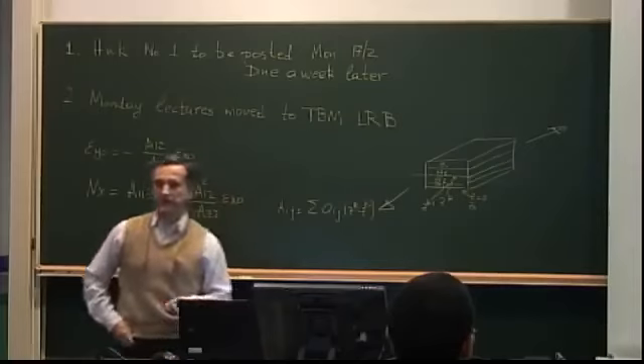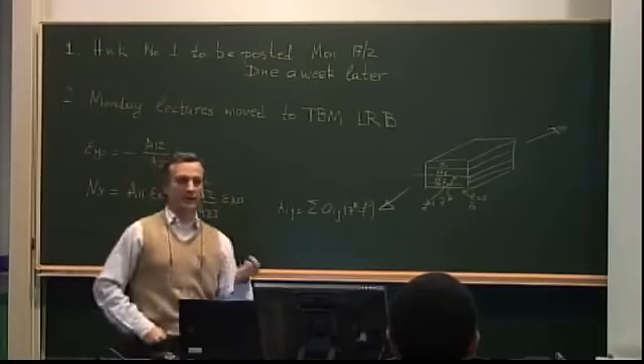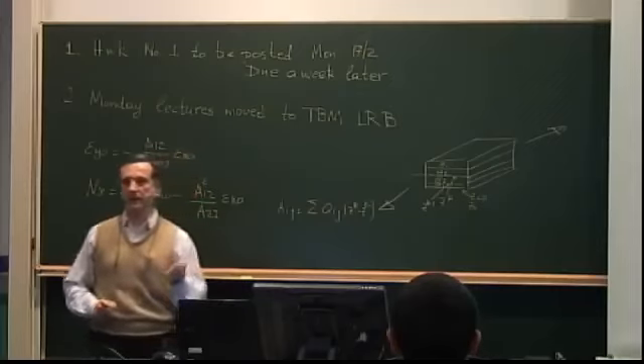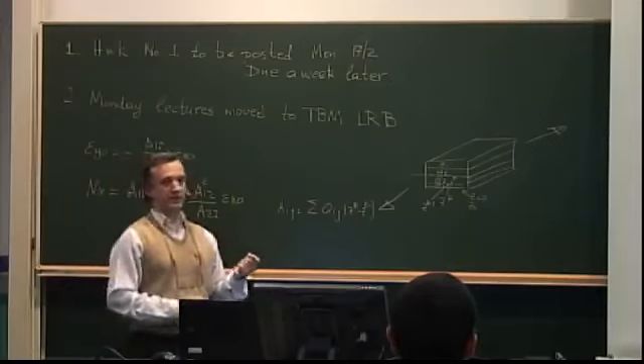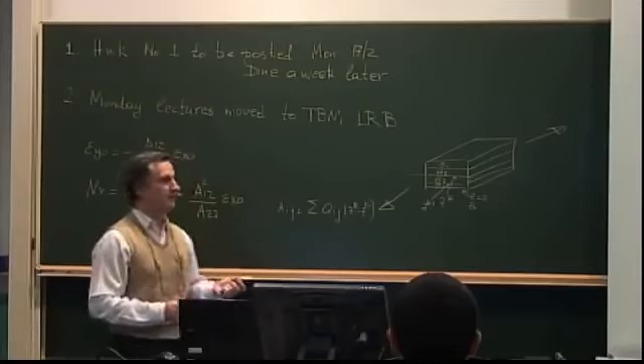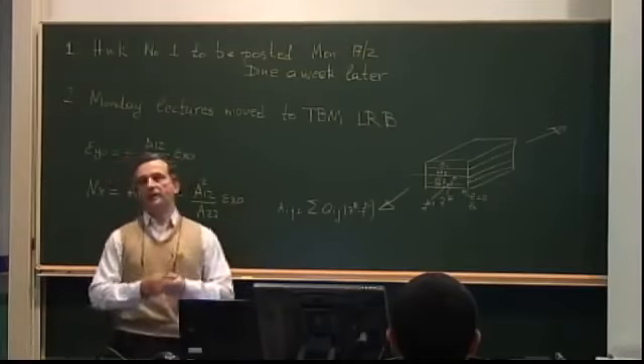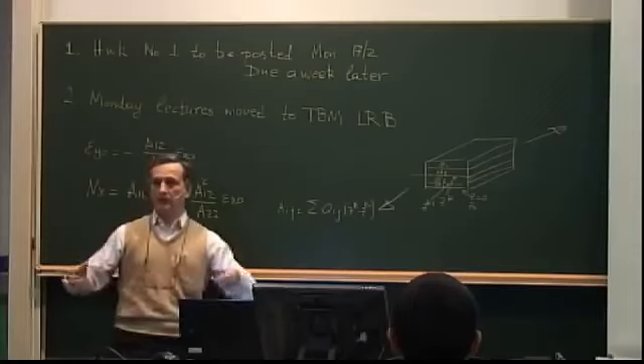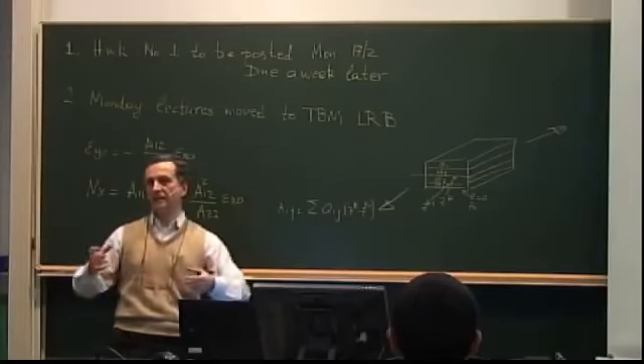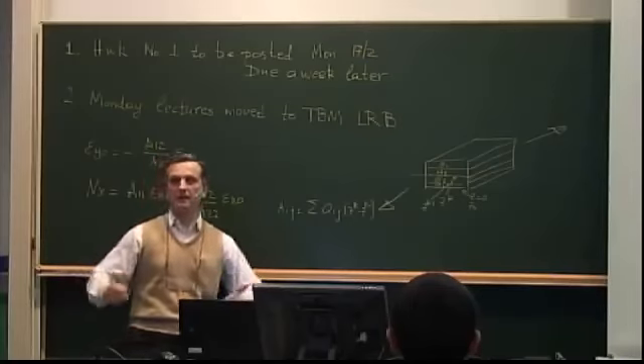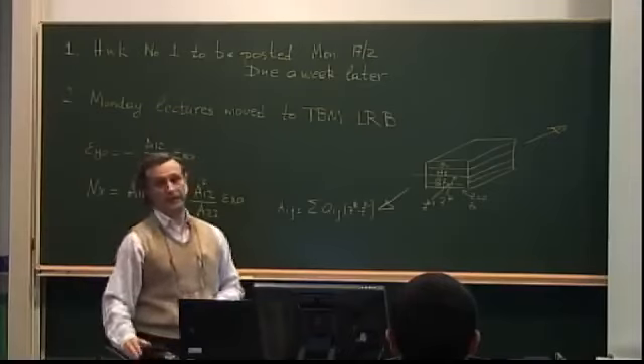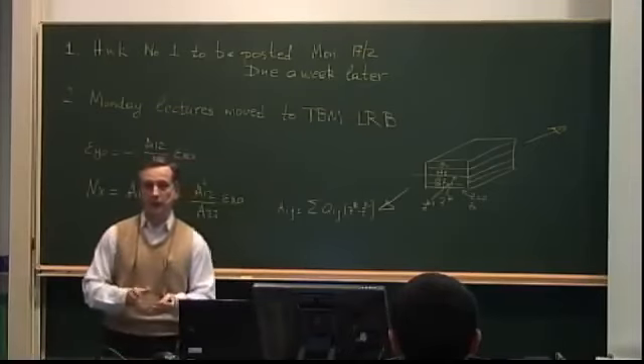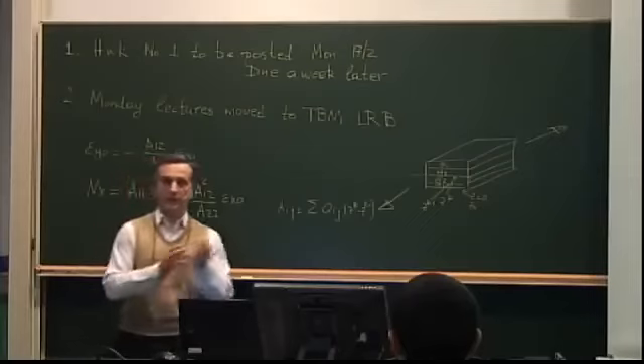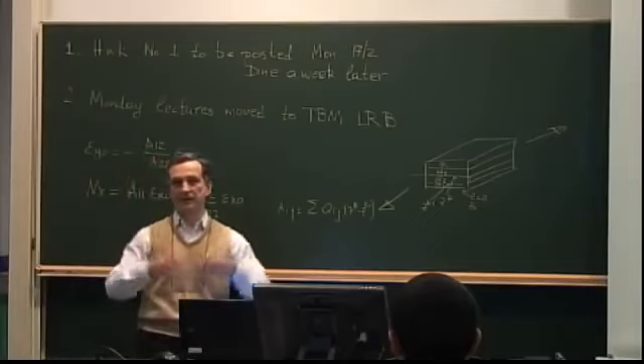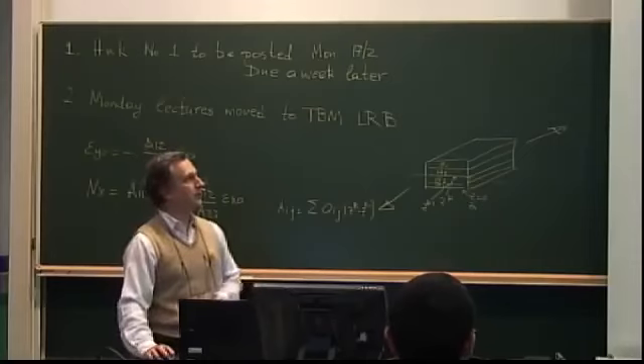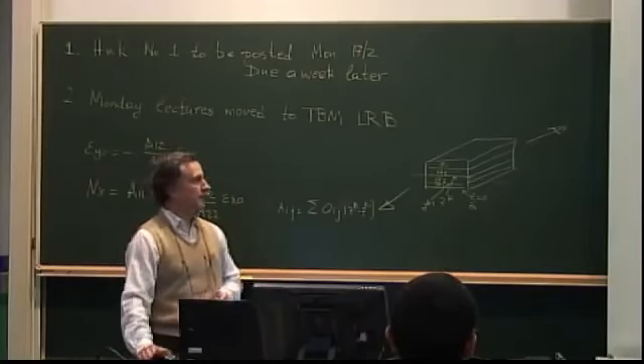And as you can imagine, if it's not a very strange stacking sequence, then that failure does not mean that all the fibers around that failure will fail. So load gets transferred from the matrix that broke to adjacent fibers through matrix that's still intact, or even through the broken matrix, and you can still carry load. And in fact, you can move load away from the plies whose matrix has failed to other plies, and then behave as if you had absolutely no knowledge of that local failure.